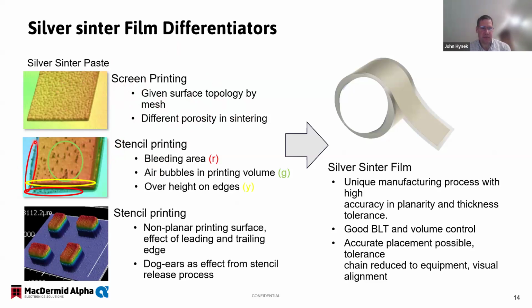So you can see here where during the placement process, or even before the placement process, the paste starts to migrate a little bit from where you want it to the outsides, because it is a paste, it's liquid format, so it'll come out to the outsides. There can also be air bubbles left in the printing volume, and this can be really difficult to control, especially as your operation goes on and you're mixing different jars or different syringes of paste together. These types of things can come and go, and they can be really difficult to control. So that's air bubbles, and that includes scratches and other little